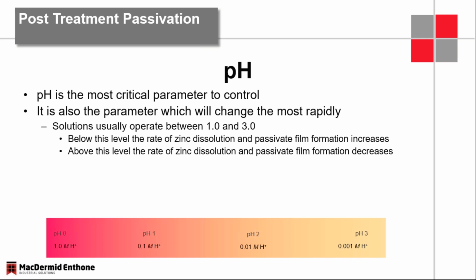Some require 30 seconds of immersion. I used to have a hexavalent chromate that was 15 seconds and no one could control it because it was too fast. pHs that are higher is going to form that film slower. Sometimes you want that. Depends on what you're trying to do with the Passivate itself.